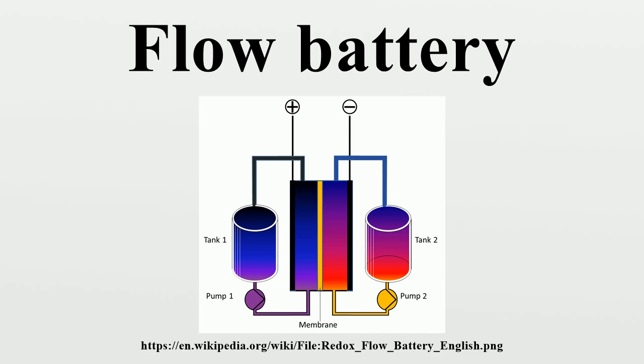The cell voltage was 1.2. The cell's efficiency exceeded 99%, while round-trip efficiency measured 84%. The battery has an expected lifetime of at least 1,900 cycles. Energy density was 19 watt-hours per liter.